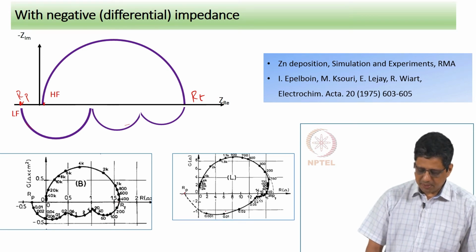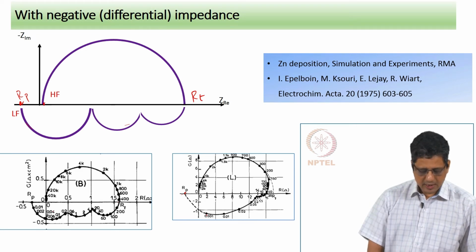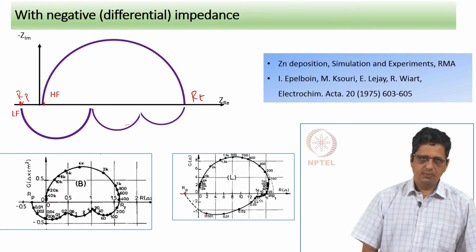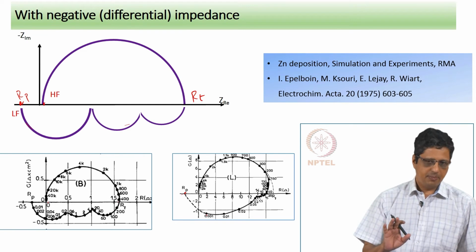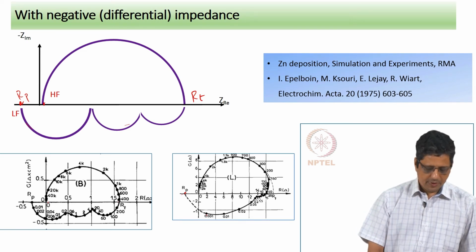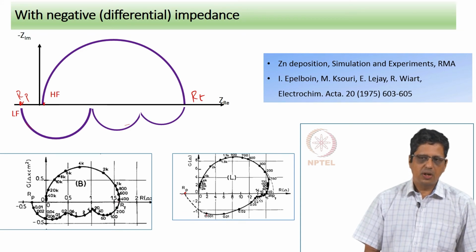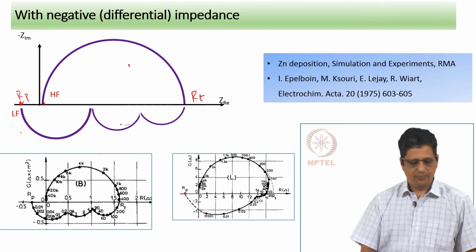So, you can say experimentally they have seen data up to this. They do not have conclusive proof that it will settle here, but most likely if you model this you can see that it would settle here. Simulation definitely they have seen, that means in mechanistic analysis it is possible to propose a mechanism and come up with a set of kinetic parameters such that a negative polarization resistance can come with the impedance data in the complex plane plot occurring in the first, fourth and third quadrant only. Okay.